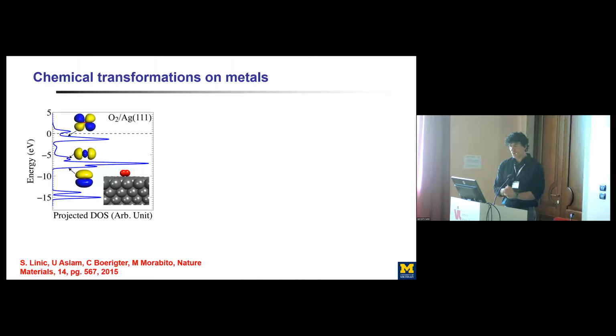So when we think about chemical reactions on surfaces, and these chemical reactions on surfaces drive really a large fraction of our economy through catalysis, we think about thermal processes mainly. Here I show a molecule of oxygen adsorbed on a silver surface. And as you see, when this molecule is adsorbed, you don't activate at room temperature this oxygen-oxygen bond. The reason is because you have this anti-bonding oxygen-oxygen state, which is not populated.